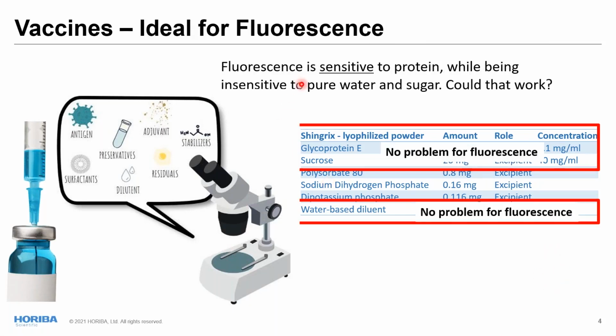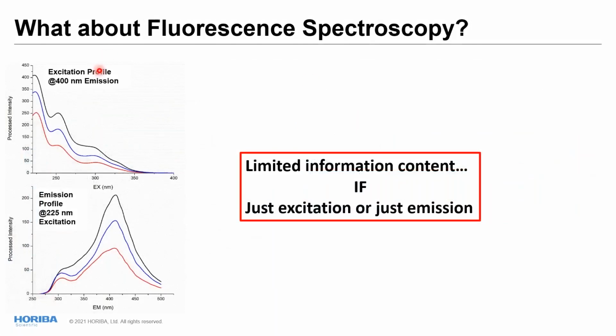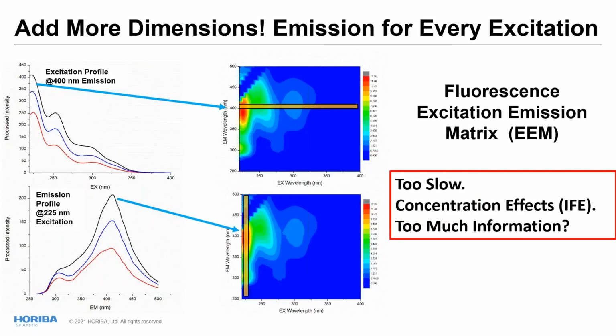So what about fluorescence? Fluorescence is sensitive to proteins, and it is simultaneously insensitive to pure water and sugars. So could that work? Going to fluorescence spectroscopy, if we look at a simple excitation profile or emission profile, just a single spectrum, we find that we have somewhat limited information content. We don't get a lot of characterization there. So what to do? I'm always one for adding more dimensions. So for every excitation wavelength, we can add a full emission profile, and then we can scan these excitations. And this turns into an excitation emission matrix, or an EEM.